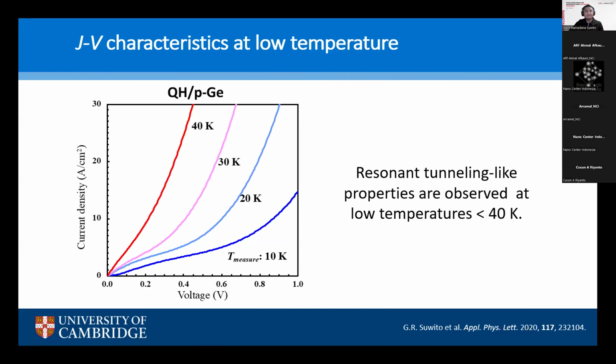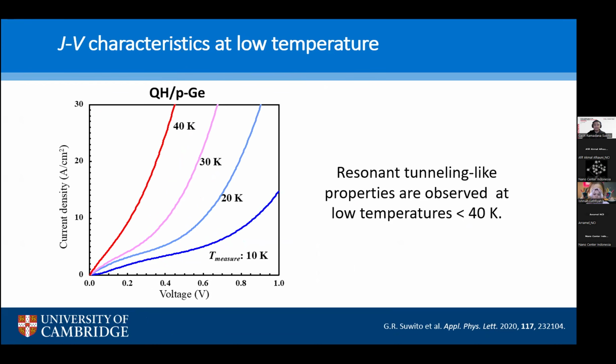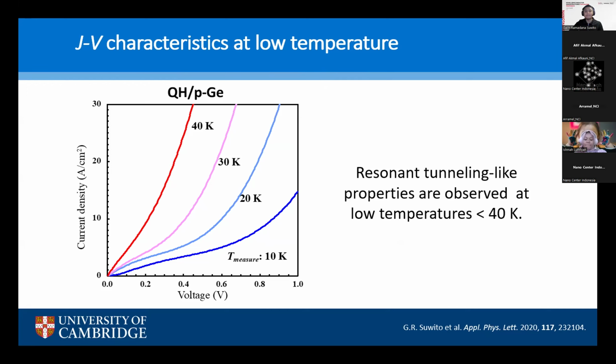Okay, so this is the result we got for the quantum heterostructures on P substrate. So at temperature lower than 40 K, we experimentally observe RTD-like properties. You can see the hump in here as well. And the trend is that as the temperature increases, the current density increases, of course, but these RTD-like properties also disappear. And this, of course, indicates the existence of what's so-called strong thermally assisted scattering at high temperatures. So therefore, we measure the other samples also at the lowest possible temperature with our system.